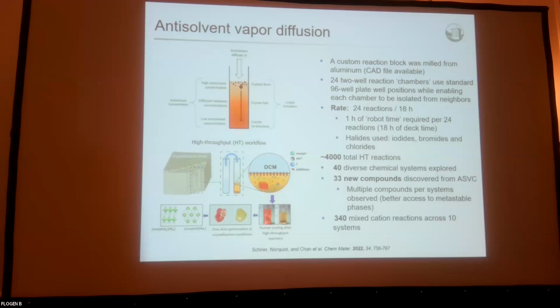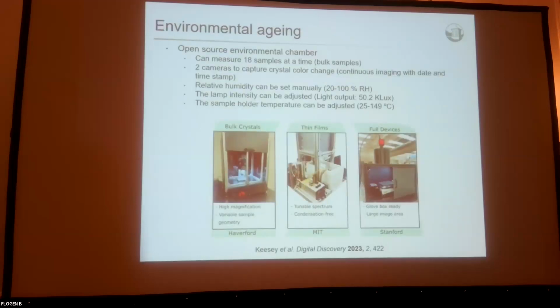A challenge with a lot of these halide perovskite instabilities, another approach that we took was to set up a mechanism by which we could do some longitudinal study. So we designed and built 3 different environmental chambers where we can do longitudinal studies, where we can control the temperature, the light level, and the humidity independently, taking continuous or nearly continuous optical images of many different samples at once, and using the optical images as a proxy for stability, we could extract degradation kinetics from those. Our setup was designed around bulk samples, but then there was another setup designed around thin films and full devices.